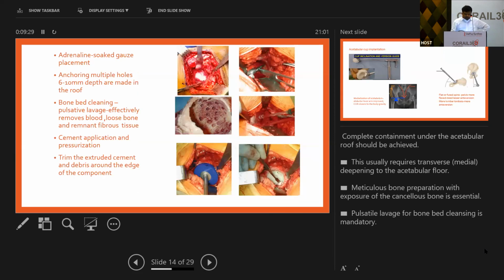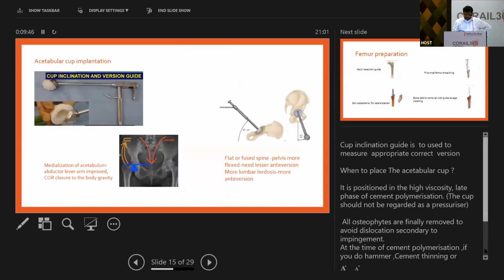For anchoring, multiple holes 6 to 10 mm deep are made in the floor or roof of the acetabulum, and then cement application and pressurization. Cement application and pressurization is good for better cement interdigitation. Use the cup inclination and version guide, for a cup 45 degrees of inclination, 15 to 20 degrees of anteversion.